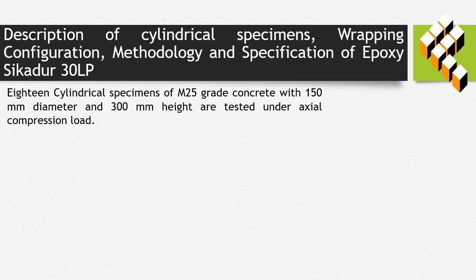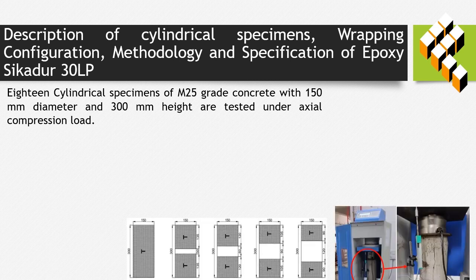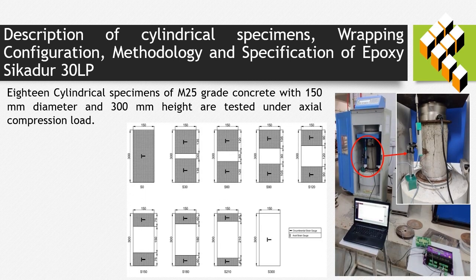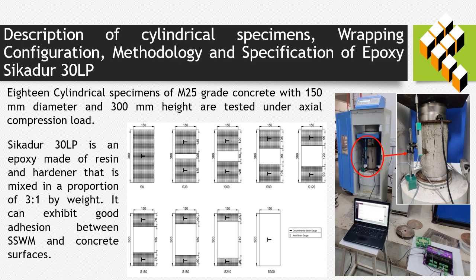A total of 18 concrete cylinder specimens of M25 grade concrete with 150 mm diameter and 300 mm height are tested under axial compression load. Different extents of SSWM confinement are considered. These include full wrapping and wrapping of SSWM strips at the ends with different gaps. The wrapping configuration and the experimental test setup are shown in the figure. The Sikadur 30LP is used to attach the SSWM on the concrete surface.